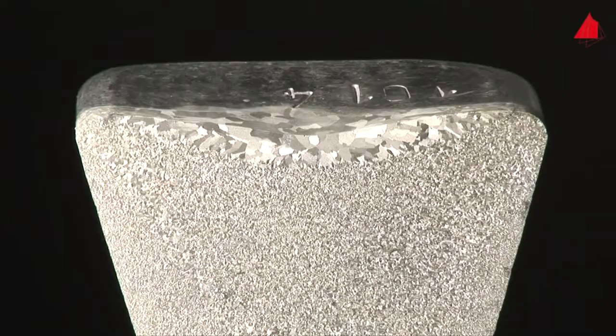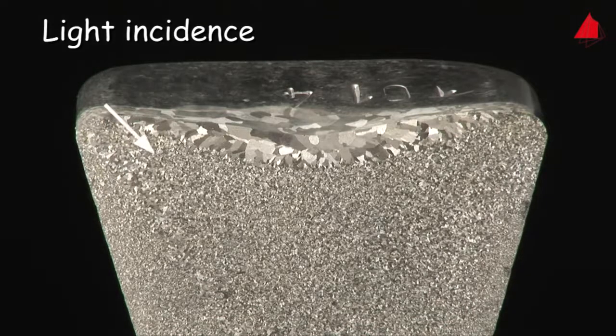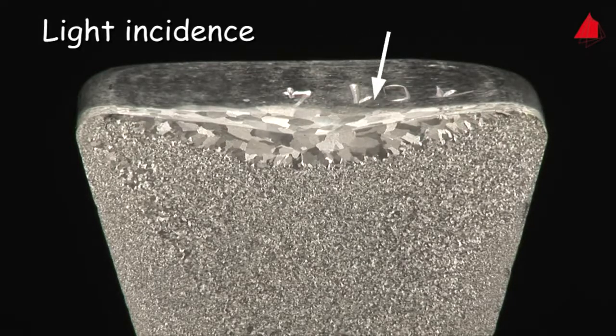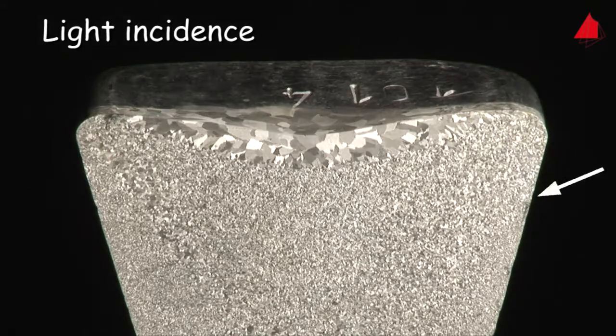Beautiful bright and dark shimmering crystals can be seen. In technical terminology, these crystals are called grains. In the central and lower region of the sample, the grains are comparatively small. They are hardly visible with the naked eye. But in the upper part, large individual grains may clearly be distinguished. But why are the grains only visible after etching? The reason for this is that the etchant structures the material grains on the surface according to their crystal orientation. Experts call it grain contrast etching. At lateral illumination, the individually structured grains reflect the light in different directions, and the grains become visible.